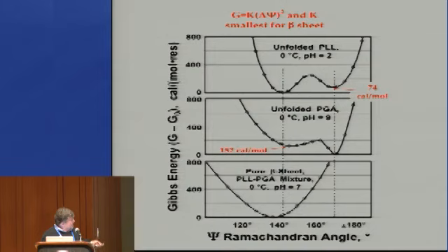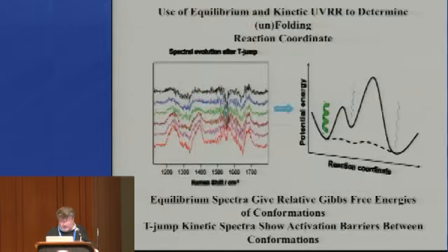And for poly-L-lysine, what you see is the minimum energy conformation is PP2. The 2.51 helix is 74 calories per mole higher in energy, you can plot out the shape of the potential function. So you learn a lot of information. For polyglutamic acid, you have a shorter side chain, and the minimum is the 2.51 helix. Now, this is old news. This is stuff that we discovered 5 to 10 years ago.